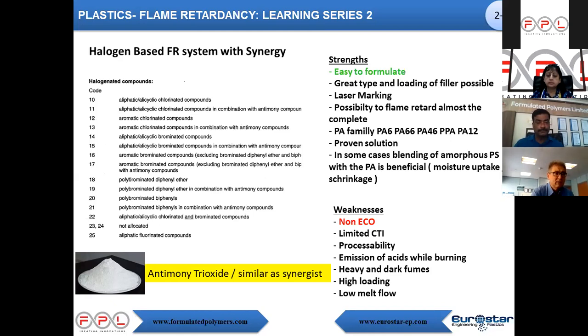And it's a material which really fumes dark and heavy. You know, when you burn, or try to burn, a material which is flame retardant with a halogen system, you feel it immediately because you see these fluffy fumes, and it's a very acrid smell. So it's not an easy one. For example, in new regulation for transportation, this is really not the material to be used.